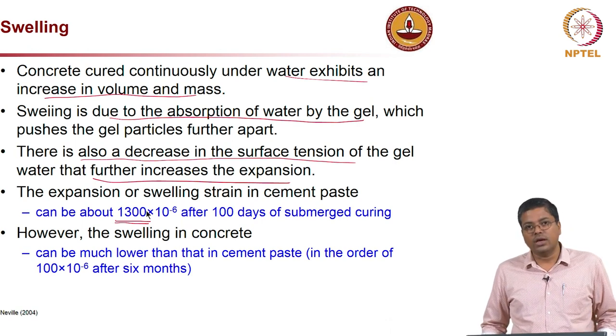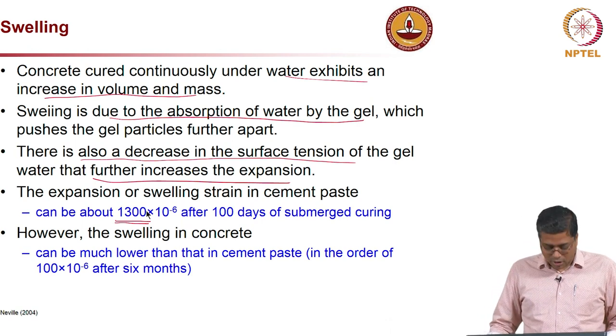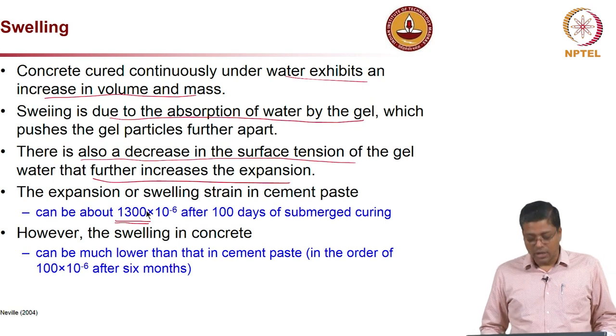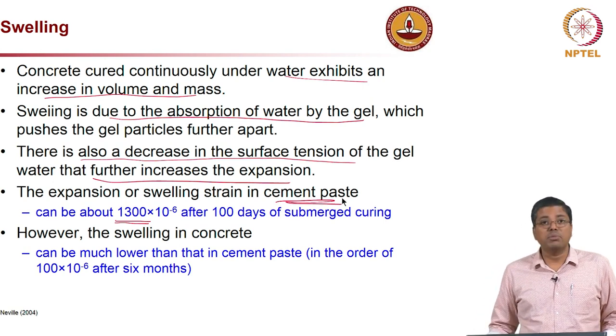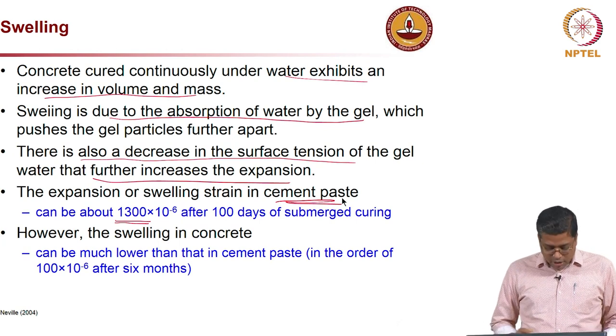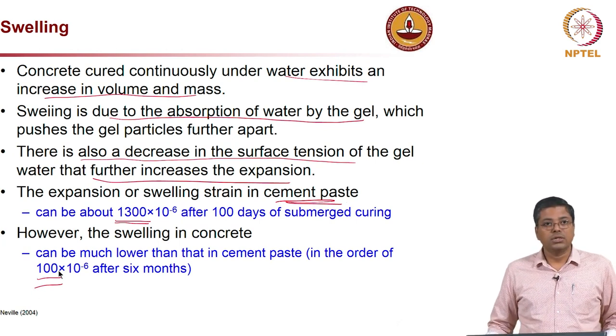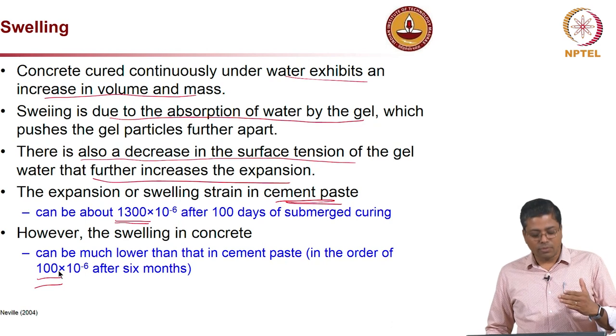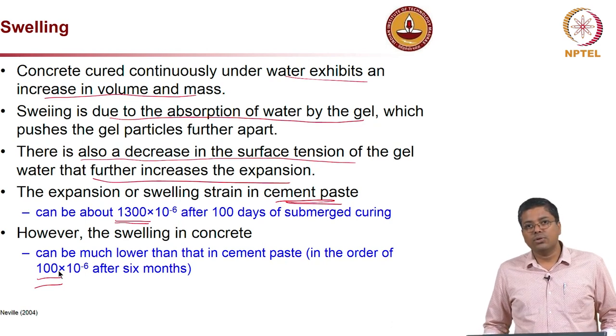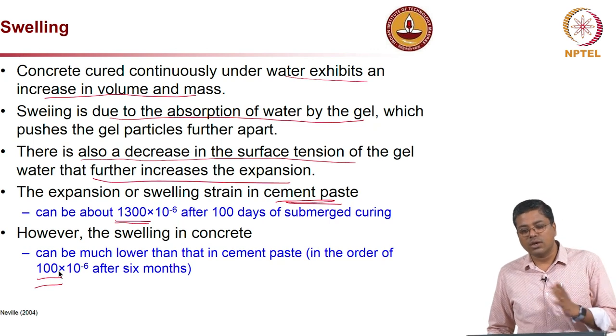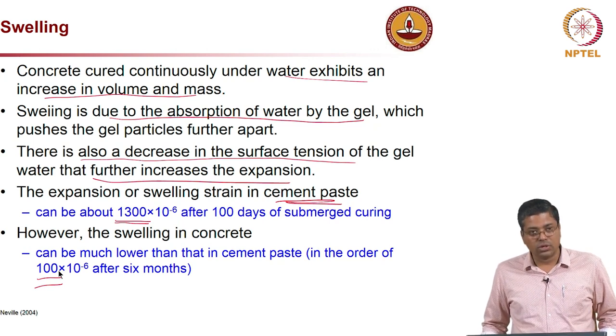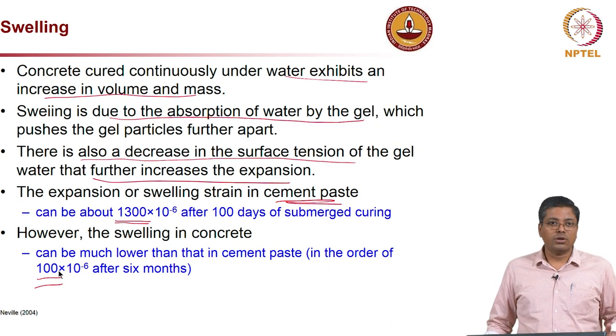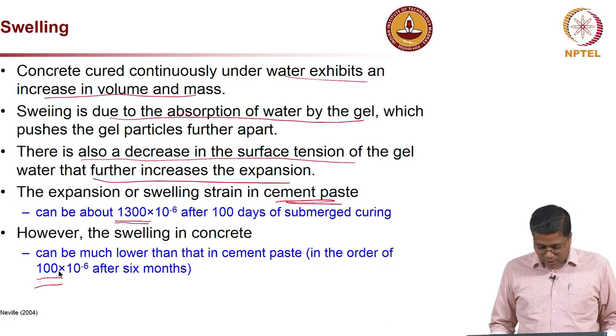So, significantly high strain could be observed depending on the type of concrete, but this is a cement paste. When you talk about concrete, it could be in this range. So, one thing to notice is, when you look for numbers, make sure that you are looking for numbers which are relevant for the concrete system which you are using and not just for the cement paste.